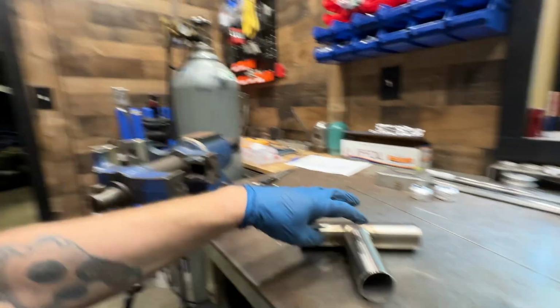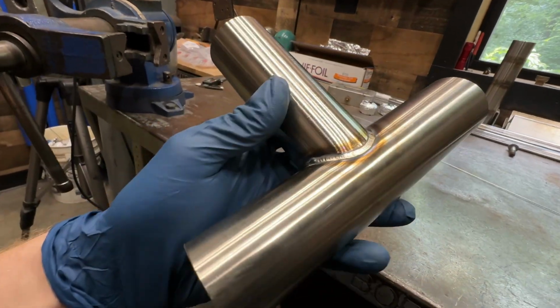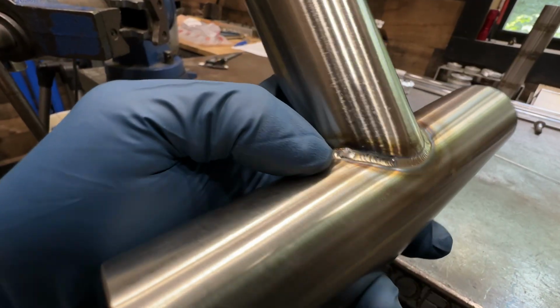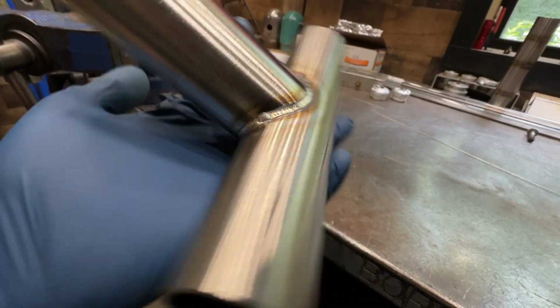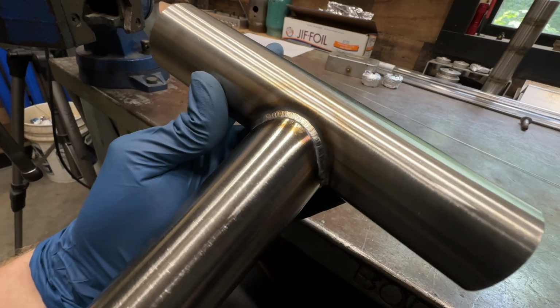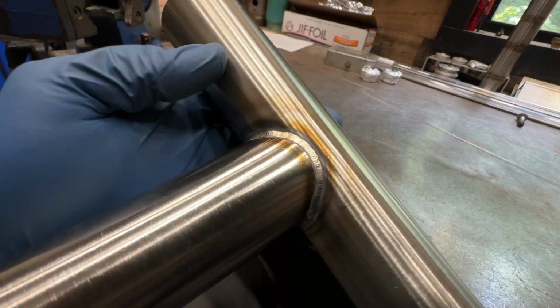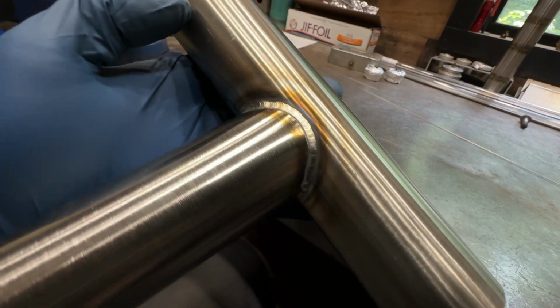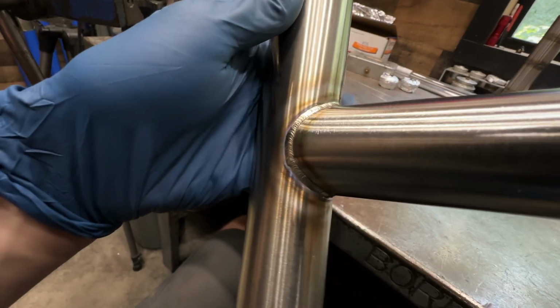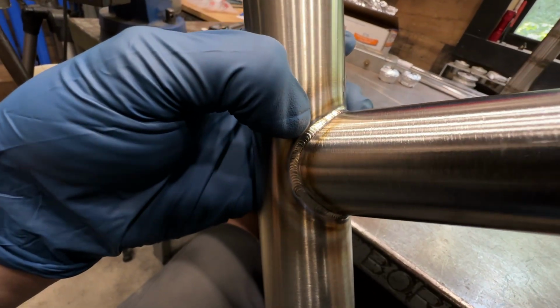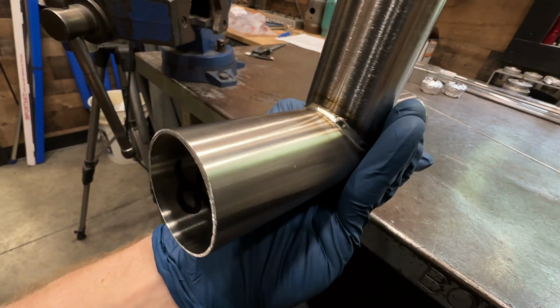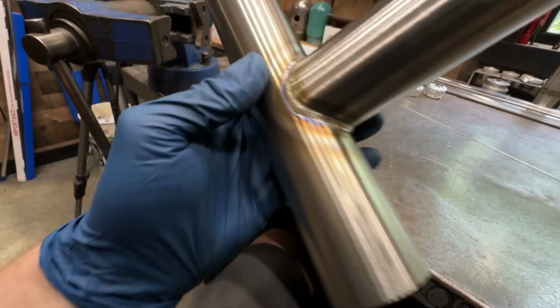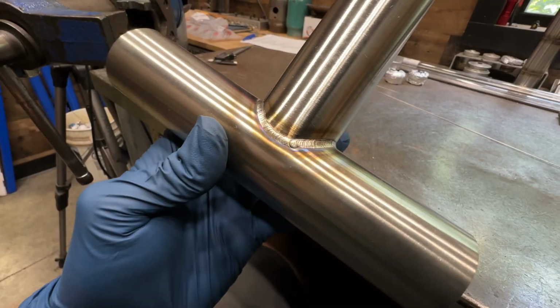The Inc 625 to stainless weld came out pretty nicely. I'm happy with it, and I'm happy with how the filler rod played with both materials as well. So on this side of the piece, starting from the initial point right there next to my thumb, this first portion of the weld was done with the 0.030 filler rod, and you can see it's a little bit narrower. And once we get over to this point, pretty much from right next to where my thumb was, looping all the way back around to the initial start-stop point, that was welded with the 0.045 rod.